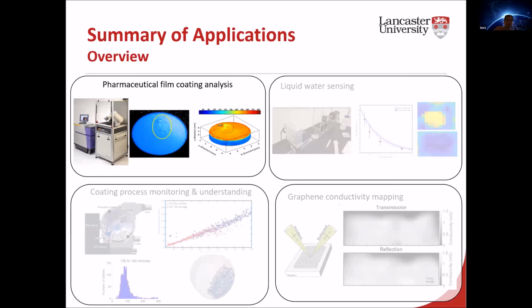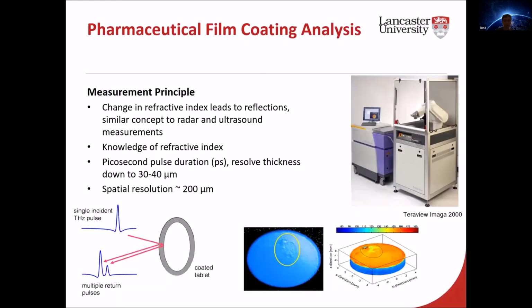So the first of which is in terms of analyzing film coatings in pharmaceutical tablets. In particular, what we are interested in here is measuring the film coatings of the pharmaceutical tablets that we take. So the measurement principle here is really based on the fact that for every change in refractive index or change in material that light encounters, you will produce reflections. So if you look at this little diagram here, at this air-coating interface, you produce the first peak, and similarly with this coating-core interface.